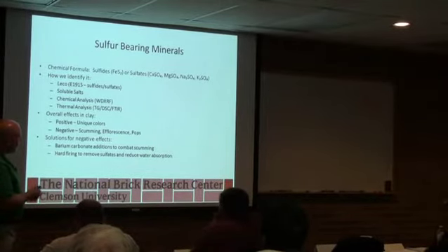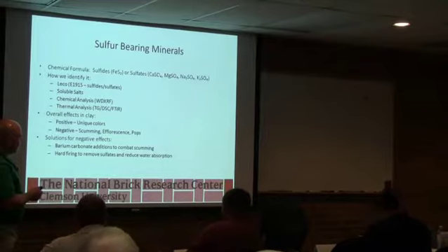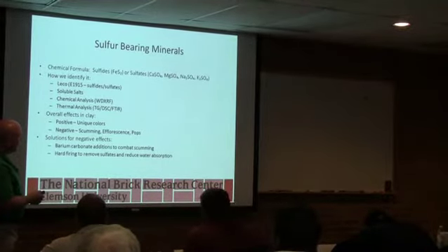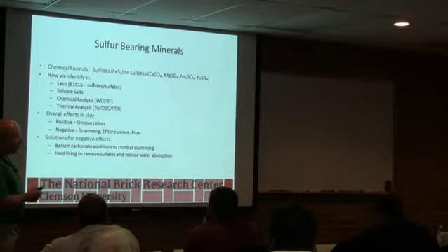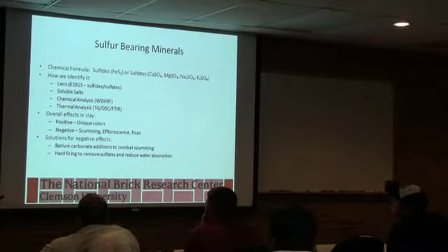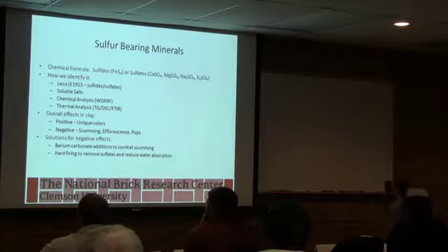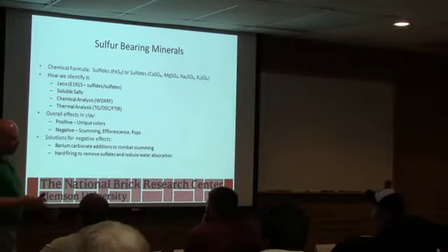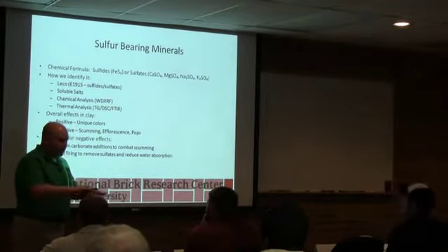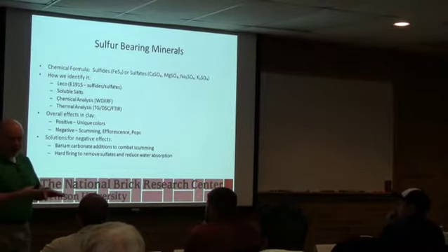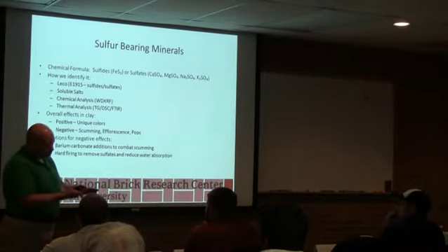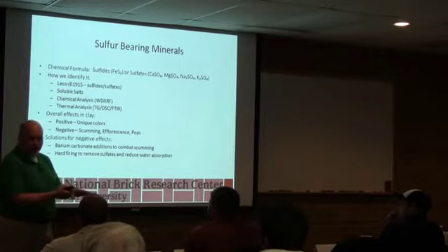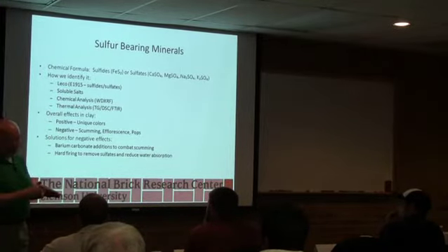The sulfates are also common. This is gypsum. Gypsum is the most common of these salts, although we see all of them. Typically we're concerned with sulfates when we're dealing with either scumming or efflorescence. Scumming is a salt deposit that may happen in the dryer, and it's usually easy to tell because there are patterns. You can see where the brick were sitting and the air was hitting the brick. Wherever the brick is drying the most, it tends to bring the most salts to the surface, and you end up with that deposit.